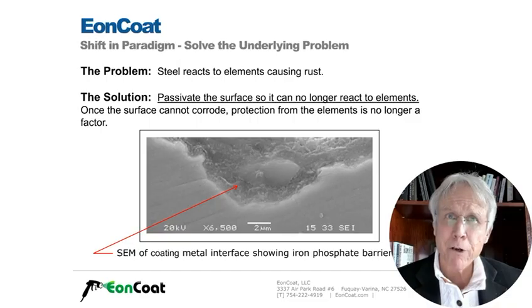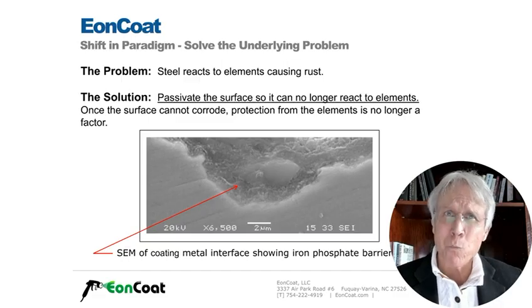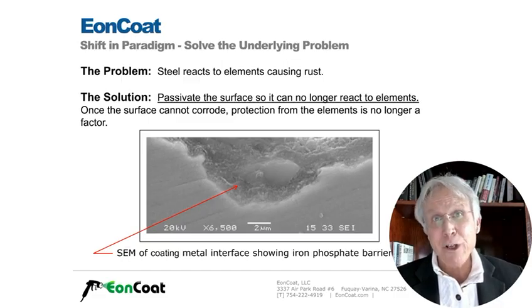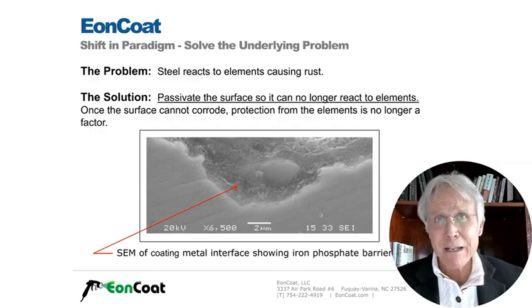If this were a polymer coating, the valley of this profile would be open because polymers stick to the peaks but don't reach down into the valleys. This causes water to roll around in those valleys if it ever penetrates the barrier. As you can see, EonCoat gets all the way into the valley and alloys the metal.